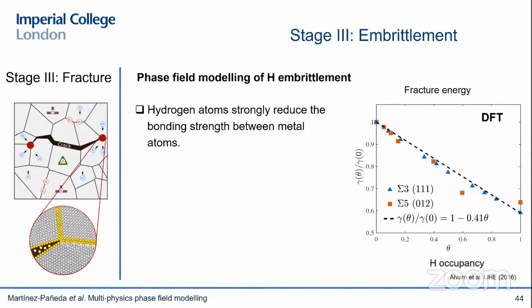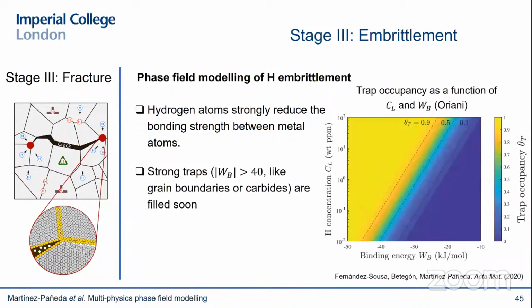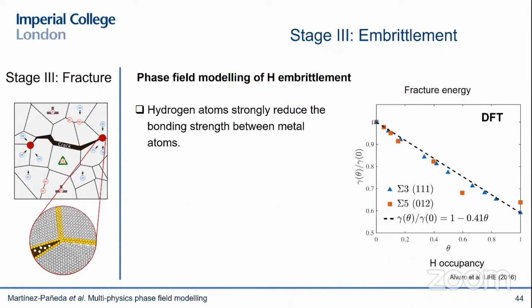That's the next question. And the answer to that comes from the combination of trapping thermodynamics and experiments. We can use Oriani's equilibrium and we can measure binding energies in our lab. And there we can plot the trap occupancy as a function of the hydrogen concentration in the lattice and the trap binding energy. And this is a parameter that we can measure in the lab. And we know from our lab experiments that grain boundaries are quite strong traps. So they have a binding energy of minus 40 kilojoules per mole. So if I go here, I can see that my trap is effectively full if I have as little as 1 part per million of hydrogen. So in other words, it is very energetically favorable for the hydrogen to accumulate in grain boundaries. And I know from the atomistics that this is going to make my grain boundaries much weaker.